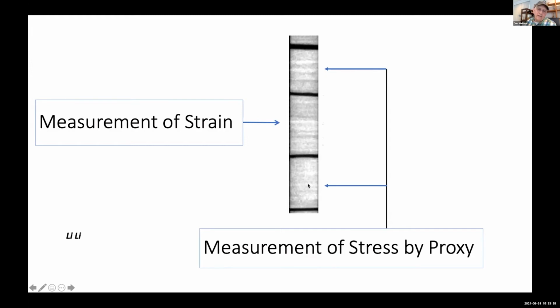because of speed. It takes us maybe a couple milliseconds to get an image. If we wanted to do stress field with diffraction, that would take us 30 seconds maybe with the beam at the bending magnet at APS to get a robust measure of the stress field in the sample. So if you use simply the images and use this as a stress proxy, you can do real time-lapse experiments. You can do millisecond kind of exposures and watch the stress field evolve and so forth.